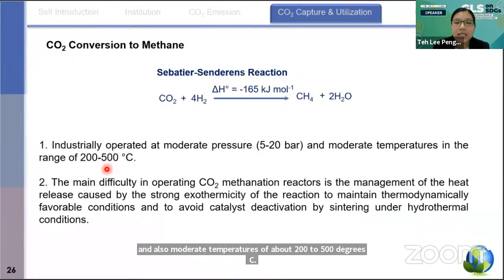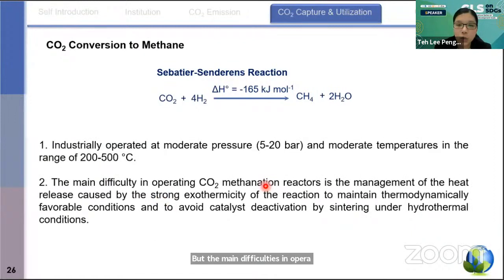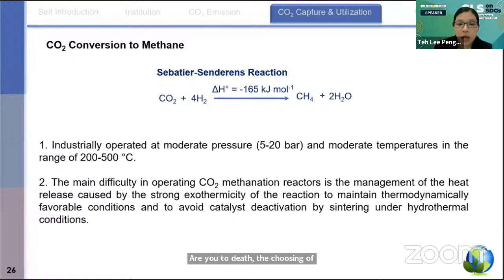But the main difficulty in operating this CO2 methanation is the management of the heat release caused by the strongly exothermic nature of the reaction, because it's very exothermic, negative 165. So by this, we need to avoid catalyst deactivation through sintering or maybe coke deposition. Due to that, choosing a very good sorbent or very good material is very important.